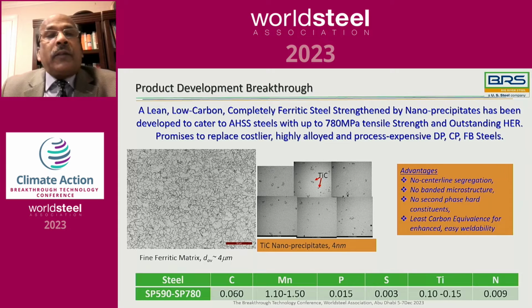This microstructure is a single phase, with no center line segregation, no banded microstructure, no second phase hard constituents. That gives very outstanding edge stretchability, or hole expansion ratio. And because it has very low carbon, it has the least carbon equivalence for enhanced weldability of the steel. You can see the chemistry is just carbon, manganese, and only titanium is added to get the nanoprecipitates of titanium carbide.